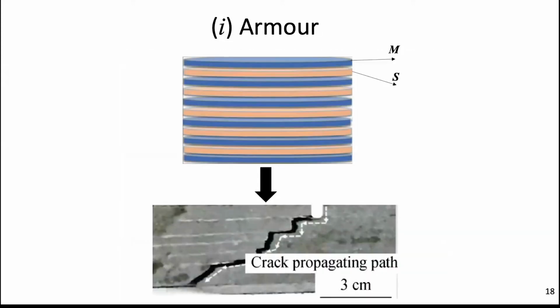When the bullet comes, in a regular non-armor material a crack will cut through the material and penetrate it. But armor materials are usually composed of layered structures where you can have a very hard material such as martensite, and I already showed you that we can 3D print martensite. But if I change the scan speed and the laser power, I can produce a solid solution, which is soft. So when I layer these materials, the cracks cannot penetrate, and I can produce an armor material.